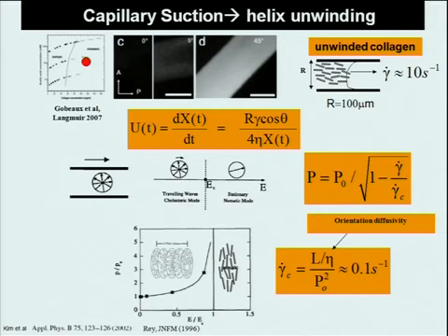So the whole point is, what's the rheology? So the key point now is this, when you do capillary suction, yesterday we were hearing about capillary suction, when you do capillary suction with a cholesteric phase, you generate capillary flow, so this is driven by this impregnation factor, and with this kind of capillary flow you can generate sufficient shear rates to destroy the helix. So here you have helix unwinding, you unwind the helix, and this is an interesting mathematical problem.